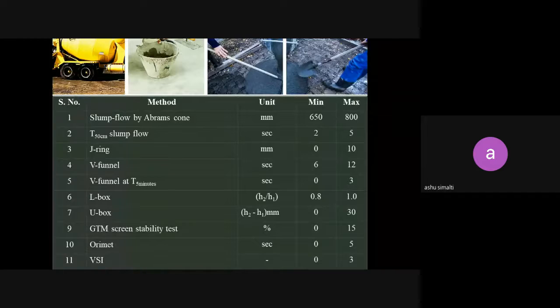L box, H2 by H1, 0.8 minimum and 1 maximum; more than 1, again repetition. U box, H2 minus H1 is 0 to 30. GTM screen, 0 to 15. Orimet, 0 to 5 seconds. And visibility index is normally 0, 1, 2, 3.